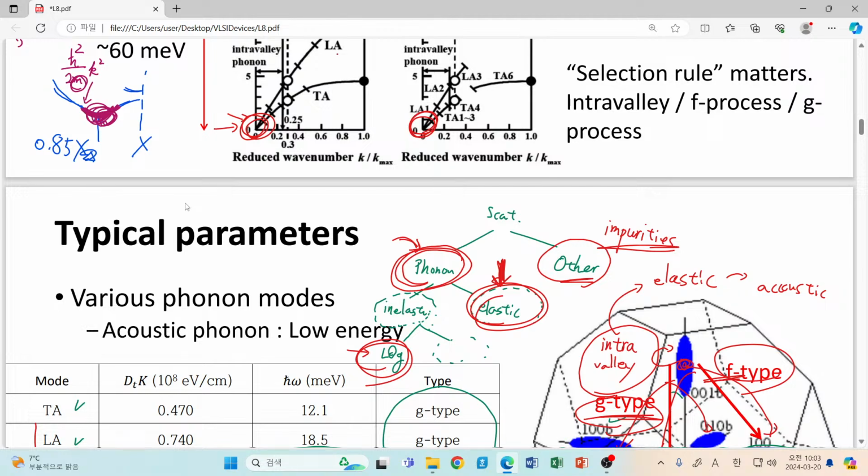The only way to kick out the phonon scattering is to reduce the temperature. Phonons are just thermal vibrations of your crystal lattice. If you reduce the temperature, the degree of their thermal movement will be significantly reduced, so the interaction between your electrons and the thermal vibration will be reduced too.